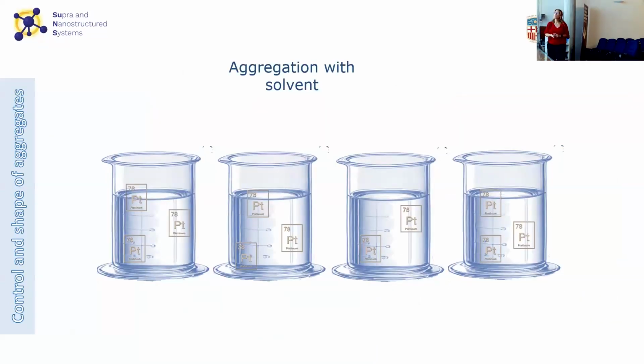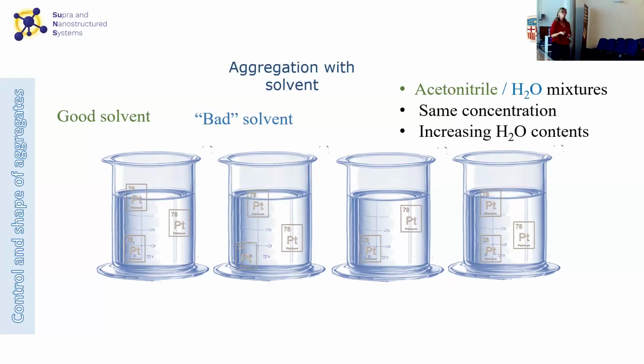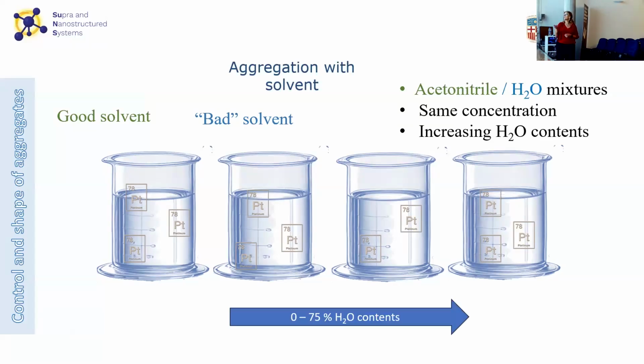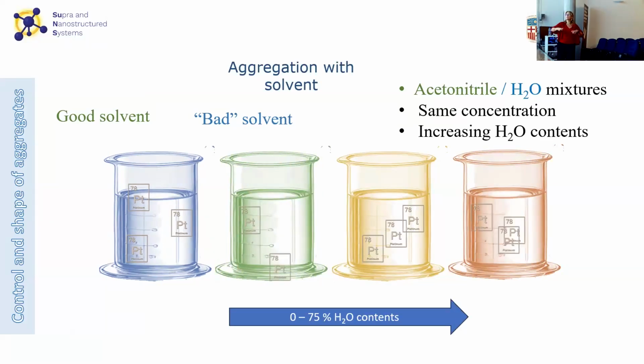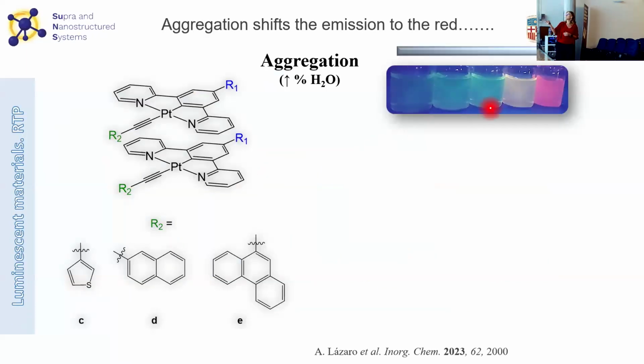So in these cases, we thought that as we already have room temperature phosphorescence, we can play with the colors. So let's induce aggregation with this mix of solvents, as I explained before. We also use acetonitrile and water. And what we observe is that increasing the water content, the proximity between the molecules induces a change of the color, as we can clearly observe in this image here.